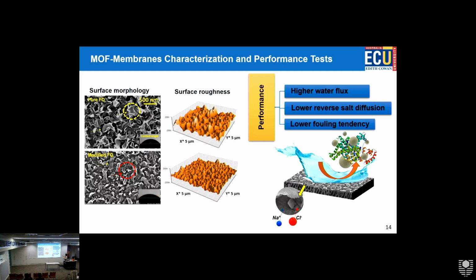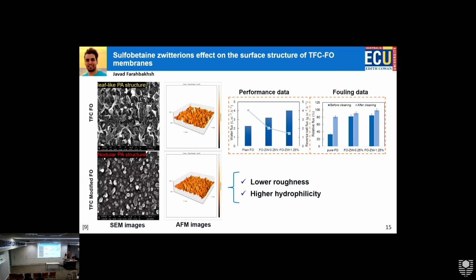So based on these results, I don't present the efficiency results, but they had higher water flux, lower reverse salt flux, and lower fouling tendency, which is advantageous for lifetime enhancement.